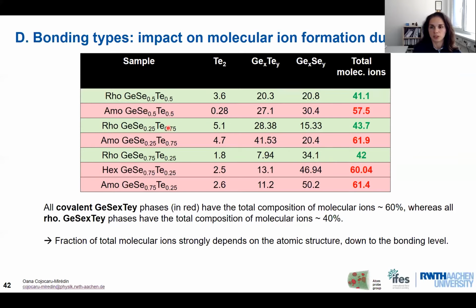The same has been observed for other compounds which have a different chemical composition but also different chemical structure. And we see nicely that the same behavior is repeated 3 times. For the rhombohedral structure, we always got a lower fraction of molecular ions than for the covalent structure. Now the rhombohedral structure is believed to have this novel bonding mechanism, which is a weaker bonding, much weaker than the covalent bonding, and of course this would be a nice explanation why we end up having a lower fraction of molecular ions detected on the detection system.